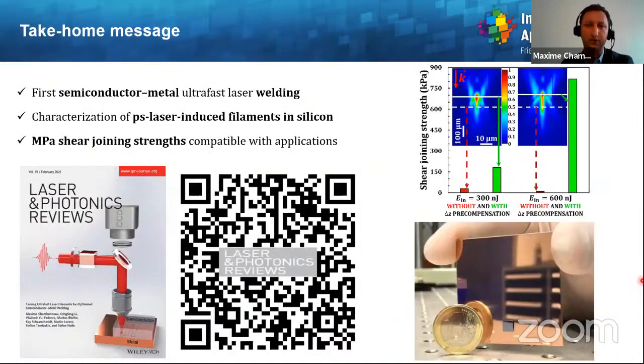Then we observed, noteworthy, that here in purple is the nonlinear propagation threshold, and one can see that no welding is possible between silicon and copper for input pulse energies below 100 nanojoules, meaning that silicon to copper ultrafast laser welding is solely achievable in the filamentation regime. So if you want to do this, you have to take into account the nonlinear focal shift and the filamentation. So here is the take-home message. We demonstrated the first semiconductor and metal ultrafast laser welding because we characterized the filamentation induced by picosecond laser pulses inside silicon. Besides, we have demonstrated that megapascal shear joining strength were achievable, which are compatible with applications.